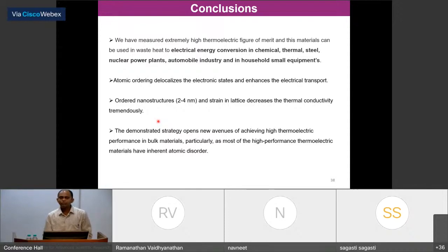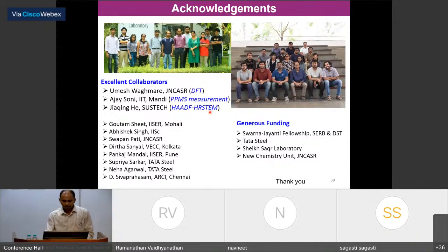But we propose a totally opposite concept. By creating ordering, we can delocalize the electronic states, and we have another handle. We can create the nanostructuring, which decreases thermal conductivity and gives rise to ultra high ZT. I hope that the community will appreciate this work. And the demonstrated strategy is a general one, because many of the materials have inherent disorder, so this can be used. And I acknowledge all my students.